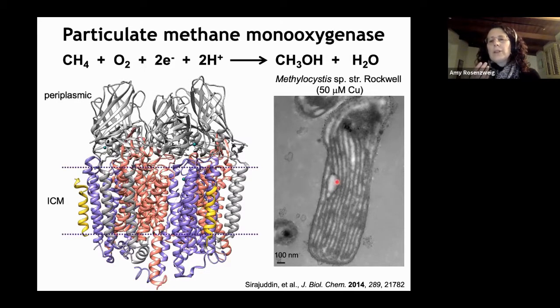The regulation of how these membranes are formed depends on copper. And even though we've known about this membrane formation for 40 or 50 years, we still don't understand exactly how copper causes it to happen. But for us doing biochemistry, it's very helpful, because what it means is that the bacteria naturally overproduce the PMMO because all these membranes are filled with it. So if we grow the bacteria in the fermenter, isolate the cells, break them open and isolate the membranes, we can get a lot of enzyme to work with.